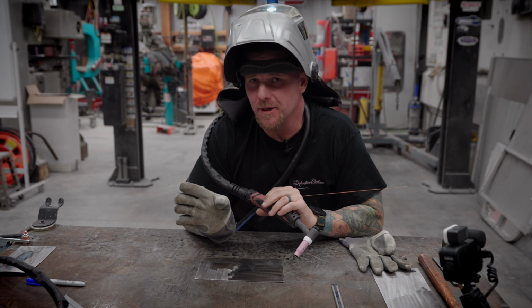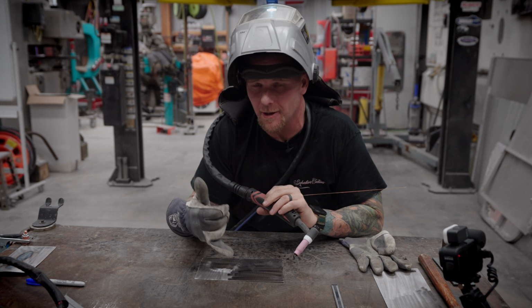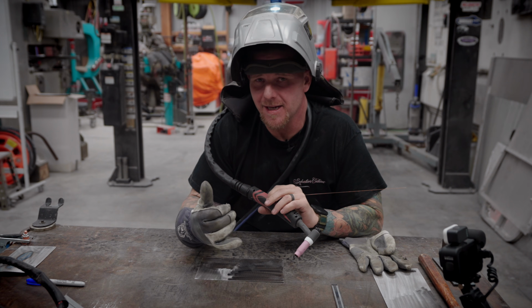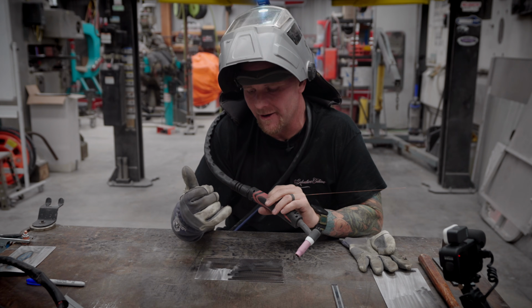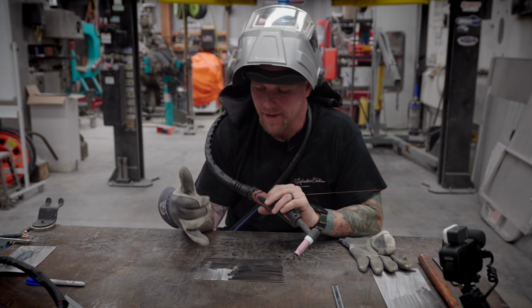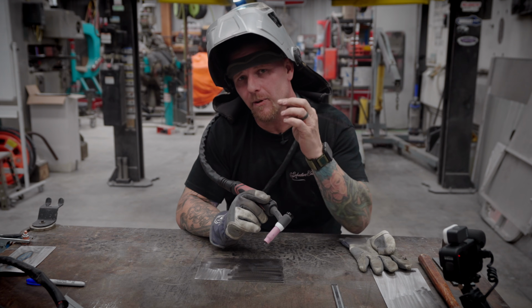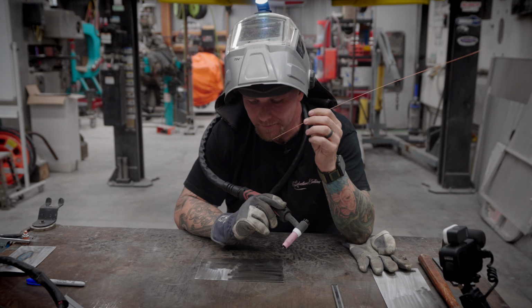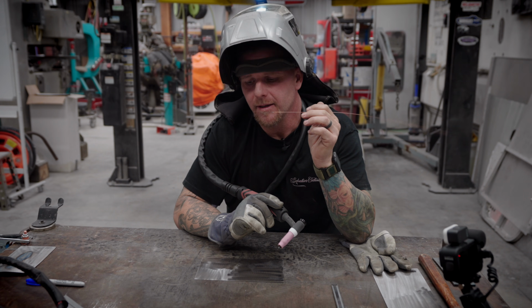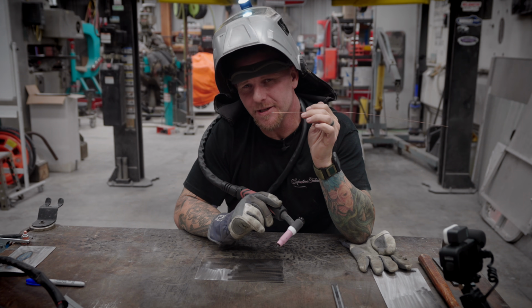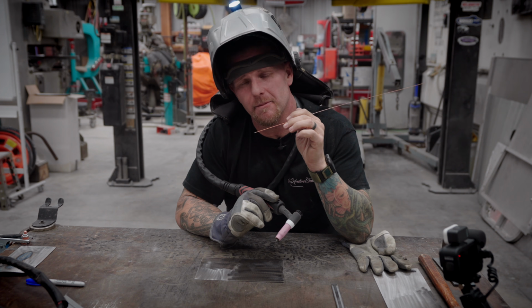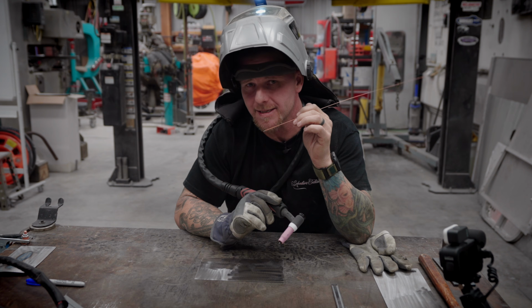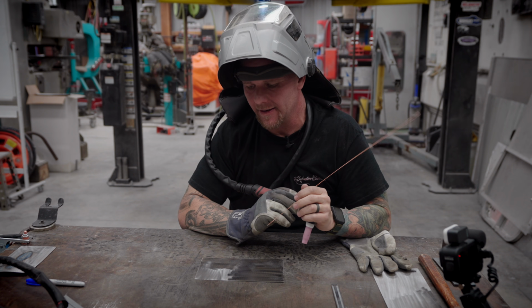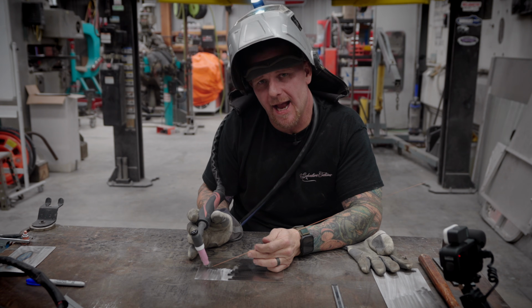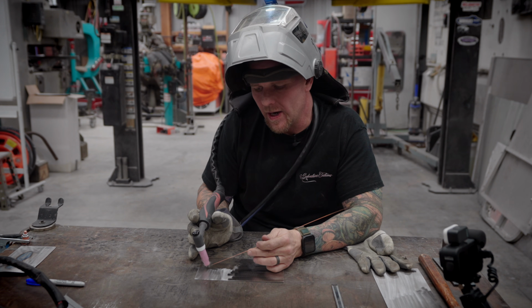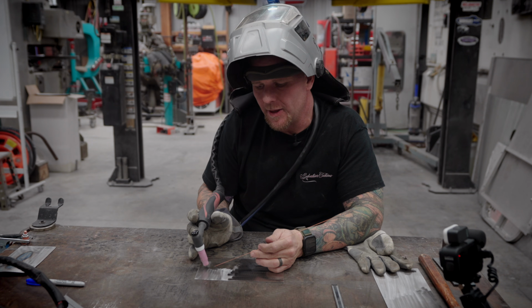We've driven it home about amperage being so important and the metal thickness being so important. The third factor to this is that the filler rod is slightly thinner than the parent metal that we're going to be welding on. So here we have 43 thousandths, and we are going to be using 30 thousandths filler rod to then melt into it. The ideal situation is that we do not have to do an excessive amount of grinding like you would with a MIG welded seam.